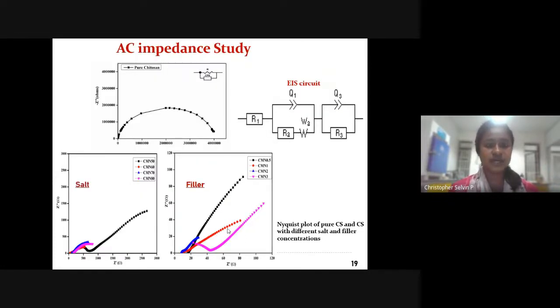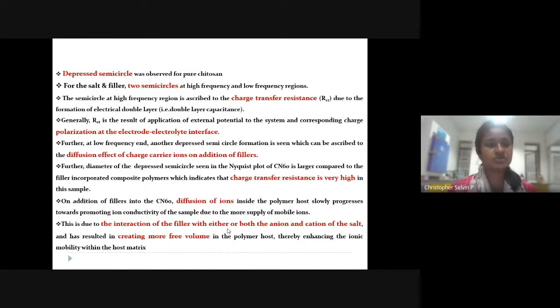Finally, we have AC impedance analysis for the prepared samples. As you can see here, these are the Nyquist plots of the pure chitosan and of the polymer with the salt and the filler, and the corresponding equivalent circuit that has been fitted. From the Nyquist plots, it has been found that a semicircle has been observed for pure chitosan, and for the salt and the filler,